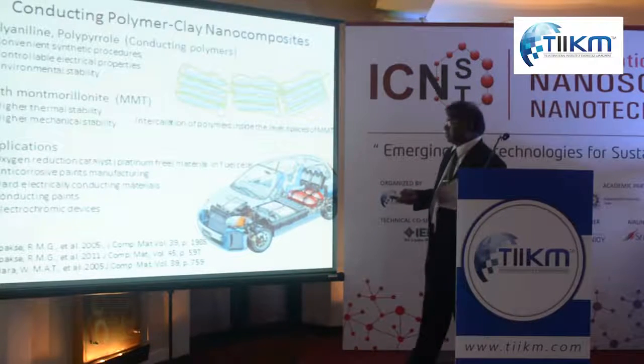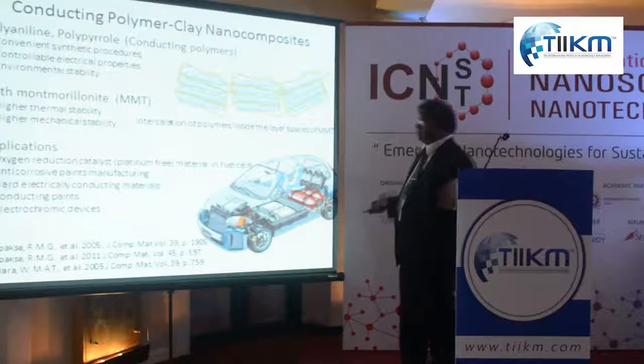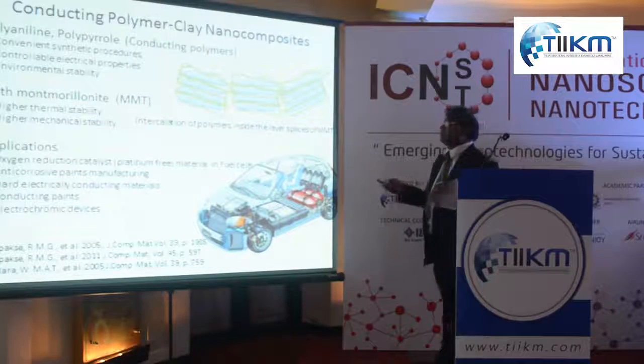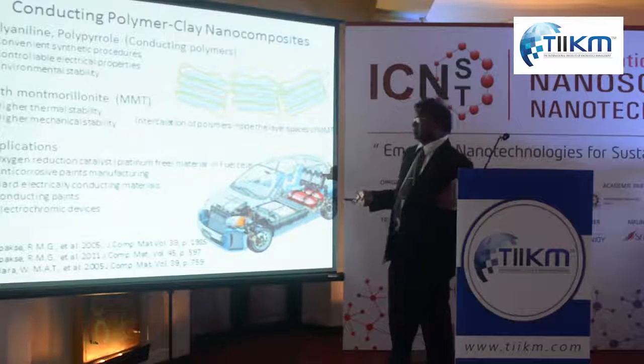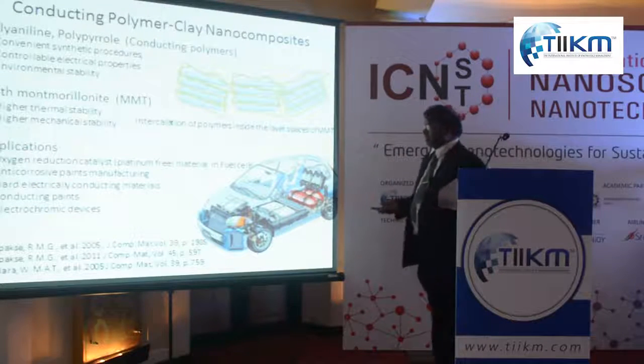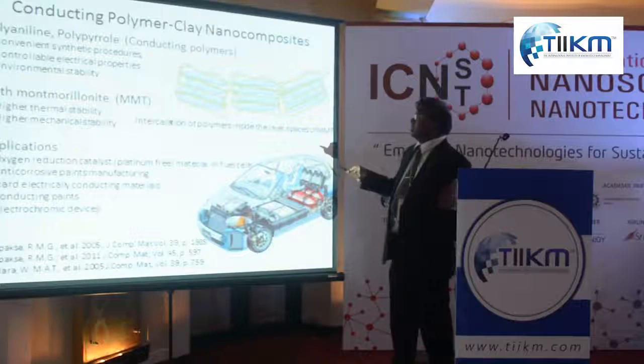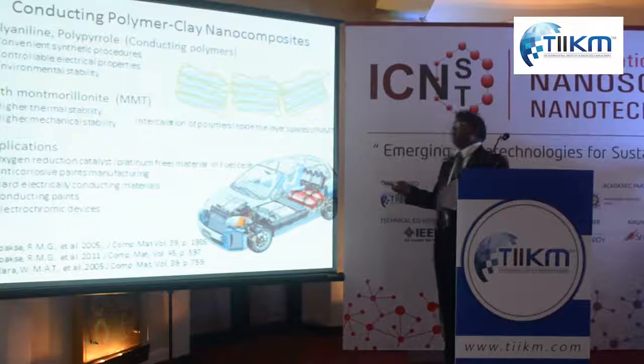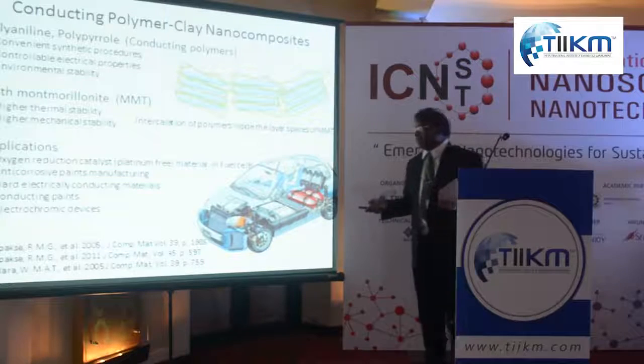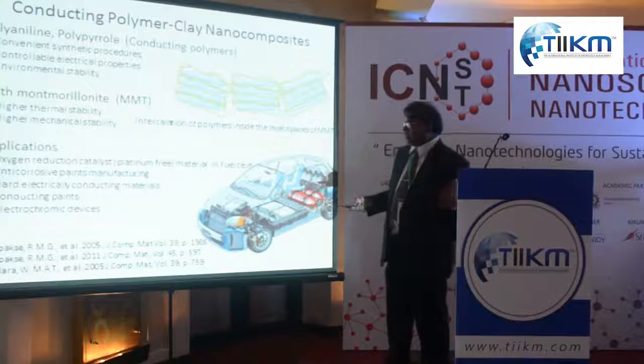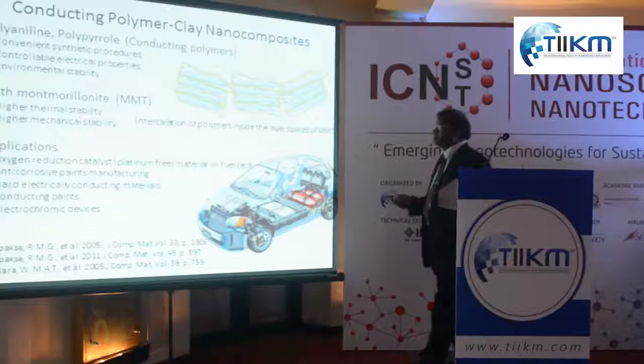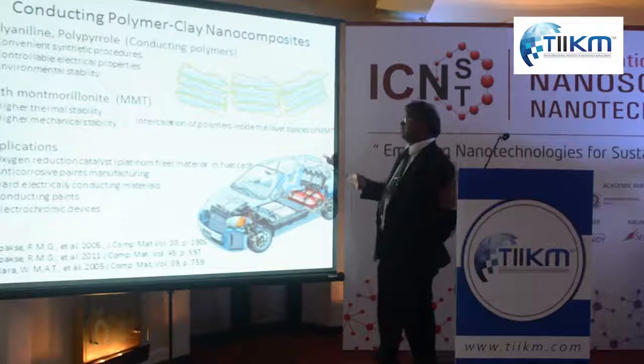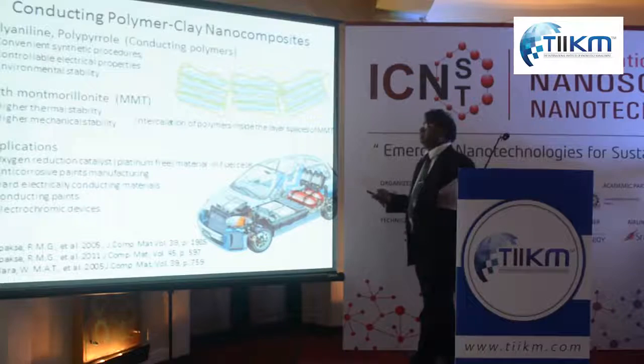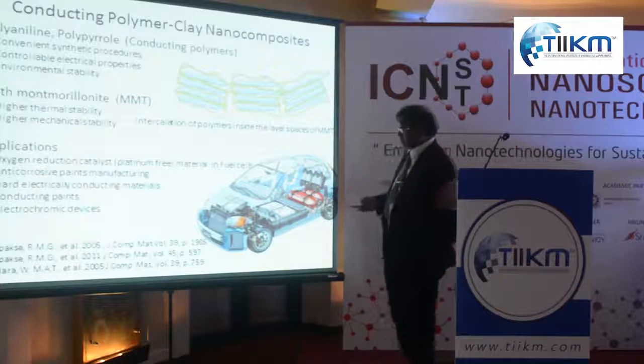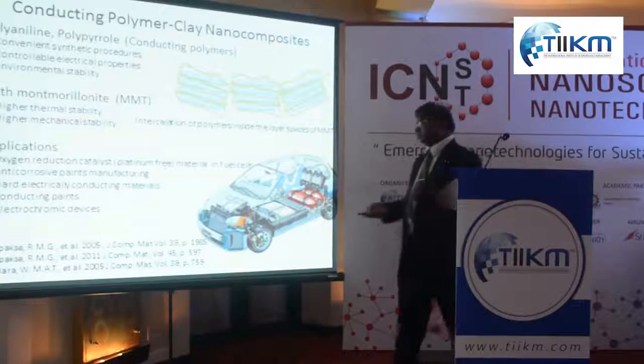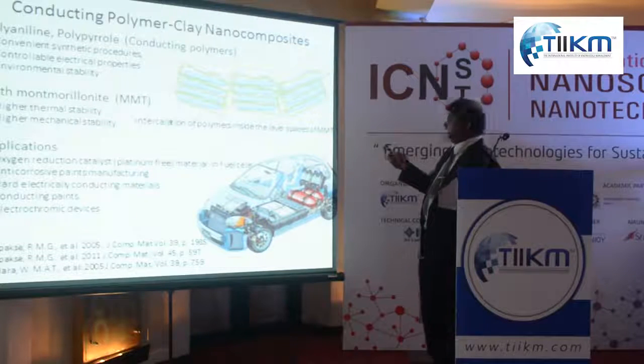Oxygen reduction catalyst, a platinum-free material in fuel cells, and we developed some of these catalysts as anti-corrosive paints and hard, electrically conductive material. The usual polymers are soft. Now when you introduce these layers of clay like montmorillonite, they become hard. And we can make conducting paints and electrochromic devices, because these conductive polymers change color when you change the applied potential, the voltage. So we published a few of those, and several other publications on these aspects.